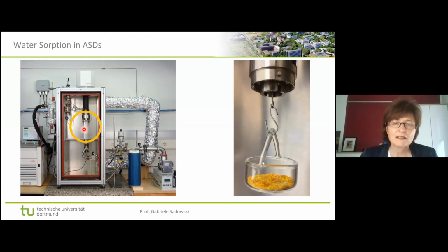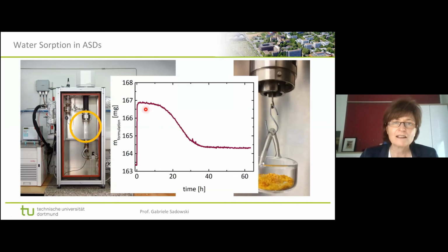The problem is if the API is crystallizing, as you have seen here, then of course we have not only the sorption, but we have also the crystallization. So in this diagram, we would use a point here, assuming that we still have the amorphous API here, and we do not have to account for the crystallization. But water sorption in pure APIs, we do measure it, and we also use this for the modeling and even for fitting our binary parameters.